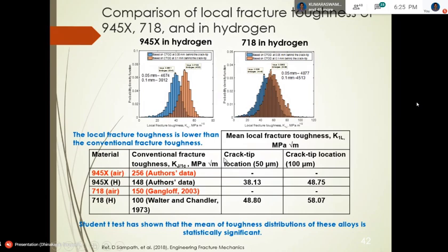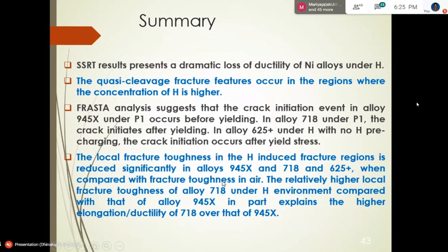So in general, what it shows is that 945X has got its fracture toughness reduced a lot compared to 718. But we need to remember 945X is especially made for oil and gas purposes. The thing is, they tried to fix one problem by eliminating grain boundary precipitation, but the failure mechanism is completely different. It was mostly cleavage and twin boundary cracking. So that's the problem with hydrogen embrittlement. Several combinations of mechanisms operate simultaneously. We need to carefully strike a balance to get a better alloy.